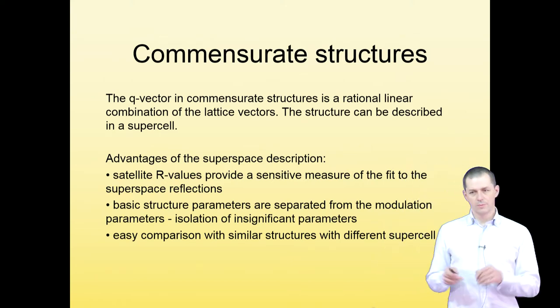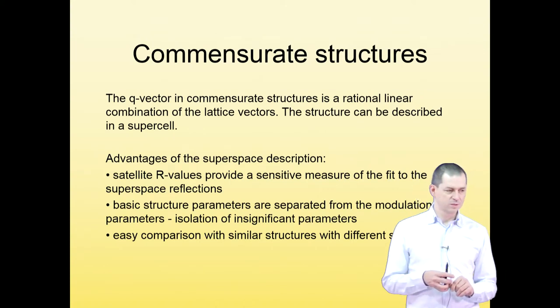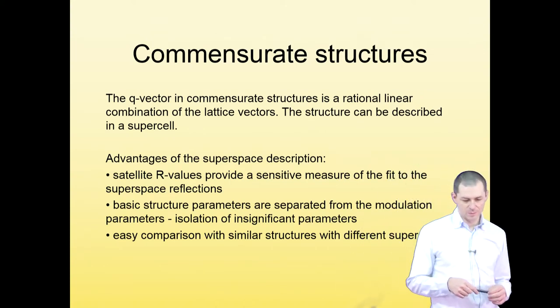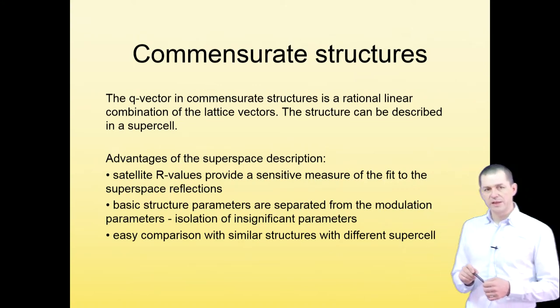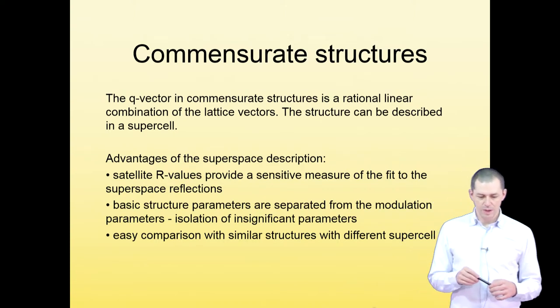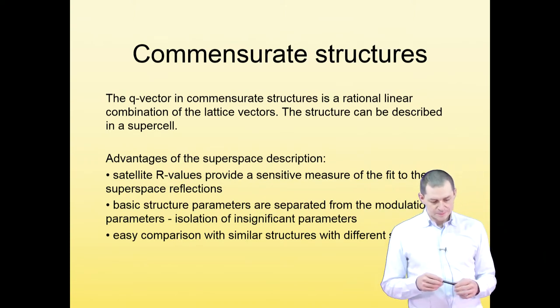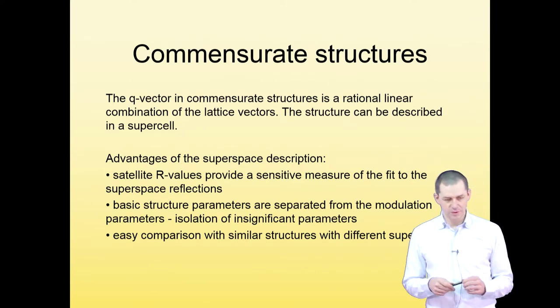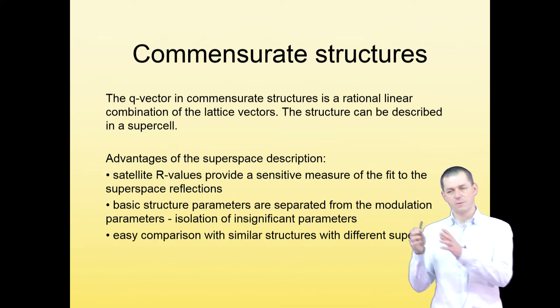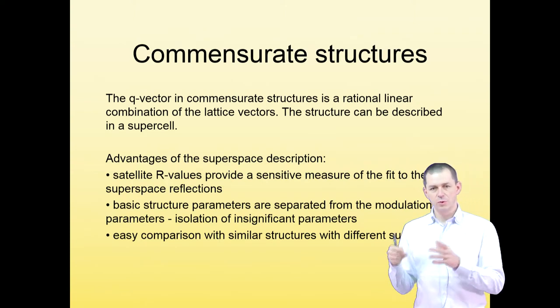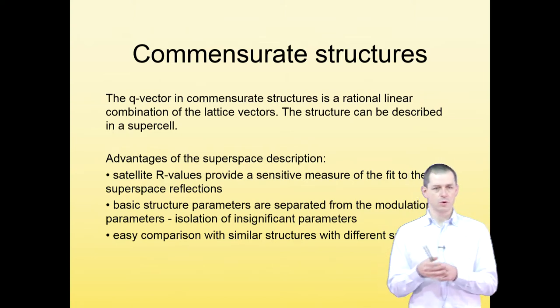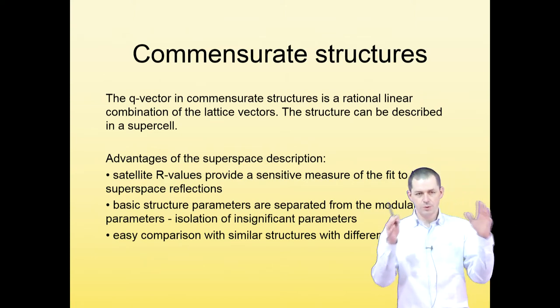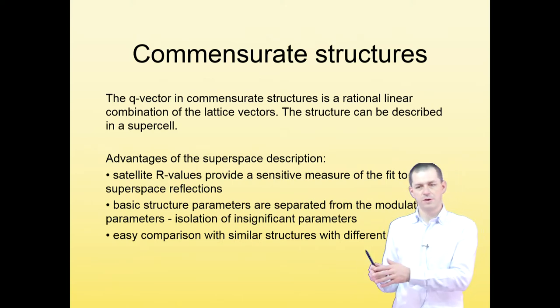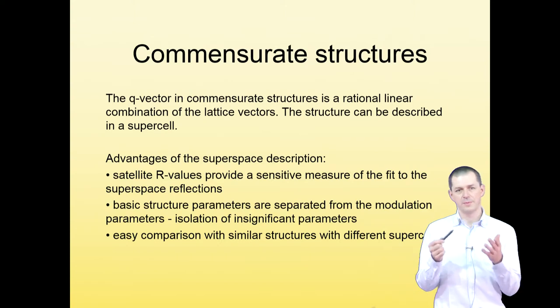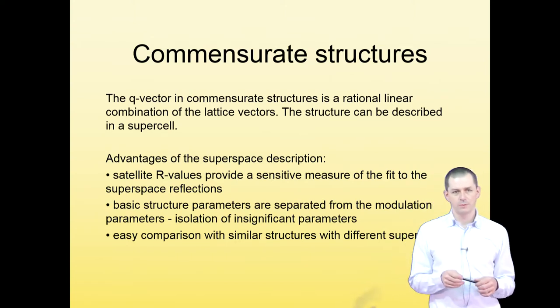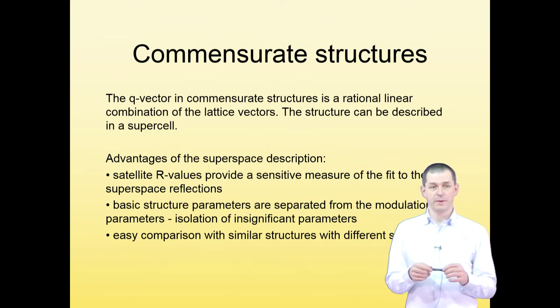And you can get rid of all the problems with modulated structures, superspace descriptions, and modulation functions. However, it may still be advantageous to describe the structure in superspace. And these advantages are that you separate the fitting of the main reflections from the fitting of satellites, and you get a sensitive measure of the quality of your description of the superstructure. If you mix together in the supercell description the weak satellite reflections and the strong main reflections, you do the refinement,